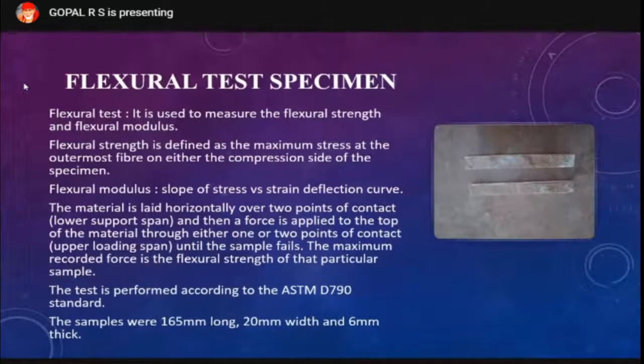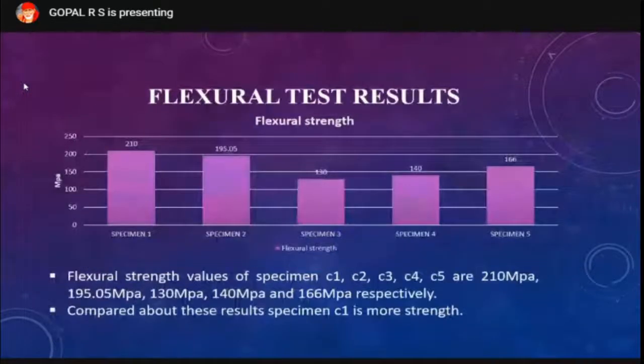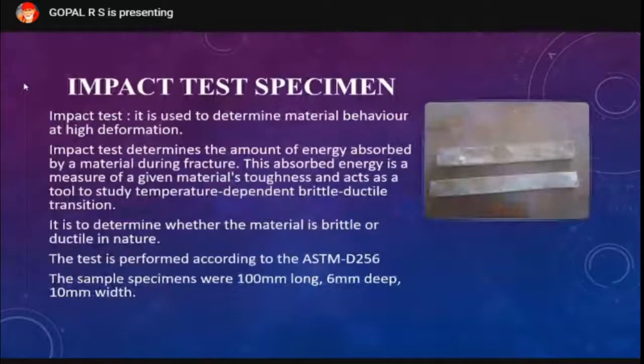The samples were 165 mm long, 20 mm wide, and 6 mm thick. Flexural strength values of the specimens are shown in the bar chart. Comparing these results, specimen C1 has more strength. Next one is the impact test specimen.